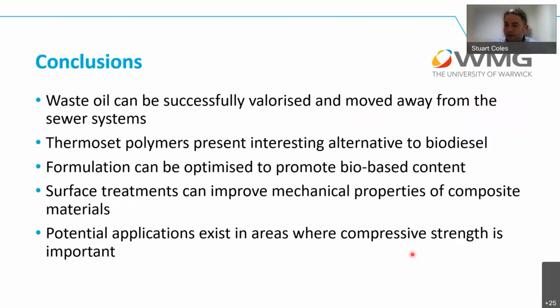And that was the conclusion of our work. That's where we got to. We got to a system that we'd optimized and then applied into impact structures and shown that, in that final point, we can get a bio-based material that has better compressive strength even after impact, and significantly higher than just having a standard epoxy material. You can do work with surface treatment. We can do some work with the different formulations to promote the amount of bio-based content that we're able to get in there.